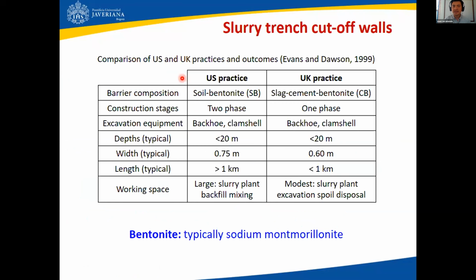Now, if we take the US and the United Kingdom as perhaps a benchmark or a framework for comparison, what you're looking at in this table is a comparison of the practices and outcomes in both places. So in the US, the most widely used slurry trench cutoff wall is the soil bentonite one, SB. However, in the UK, by far, the most widely used is slag-CB cutoffs. The construction stages are different. There are two phases in the US practice and one phase in slag-CB walls, but the excavation equipment is pretty much the same, backhoe and clamshell.